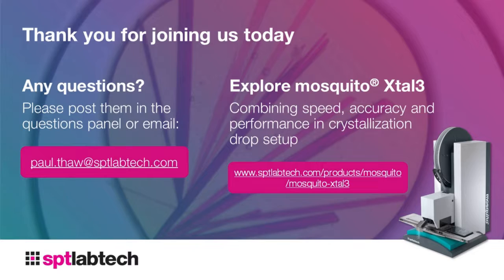First question of the day is, based on the Y19 structure of Roy, Mike, you mentioned seeding to achieve that one. How does that work with Enact? So it's a great question. There are different ways we can seed the crystallization experiment. We can either take our seeds, so assuming we've got a seed stock to start with, and dispense them in the oil itself, so that gets dispensed across the plate just as part of the oil. We could streak seed across the plate, so just literally taking a needle and streaking the seeds across the plate through those droplets to give localized concentrations of them. The options here are quite varied. We can get the seeds into the crystallization condition relatively easily, and it does definitely increase the success rate of the growth of higher quality crystals.